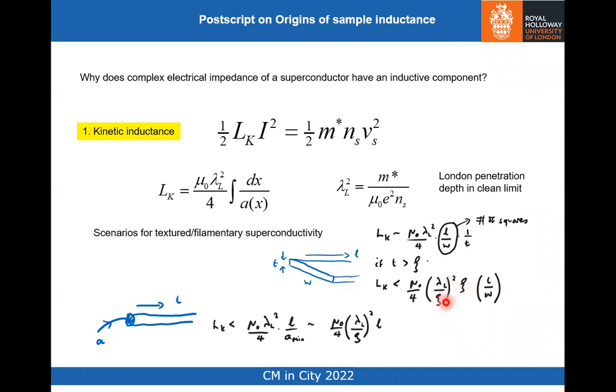And by the way, we know what this ratio is because we know more or less what the ratio of the upper critical field and the lower critical field is, and some geometrical factors. So that's something that actually needs to be explored more, but that's locally one favored explanation of what's going on. This, coupled with inhomogeneity of the sample, is accounting for a lot of stuff.